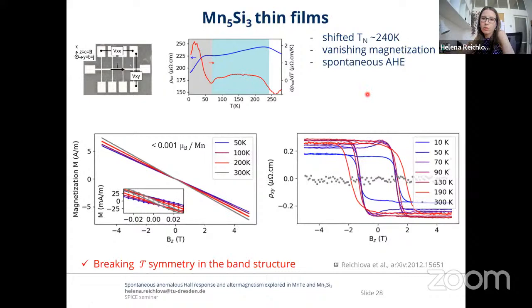This is the Hall signal, the transversal measurement as a function of the out-of-plane magnetic field sweep. And we can observe a clear, robust anomalous Hall effect present in the full temperature range when the samples are magnetically ordered, and is absent at room temperature where the sample is paramagnetic. So the clear spontaneous anomalous Hall signal shows the breaking of the time reversal symmetry in the band structure. Now I will look into it in more detail.